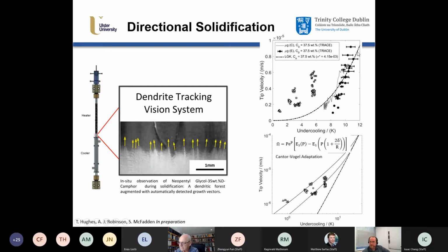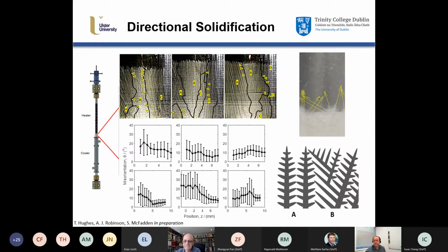They don't really fit this LGK curve. This is a modified LGK where they modified the stability parameter. But looking here and going back into the older work, the Cantor-Vogel is an adaptation to the Ivantsov theory where delta is a boundary layer. And by applying boundary layers, which are very reasonable, we're able to get agreement with the results in our case, which are performed on terrestrial results. So that's what we're looking at in that case.